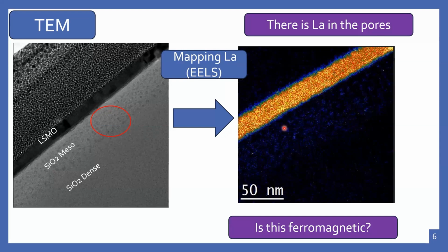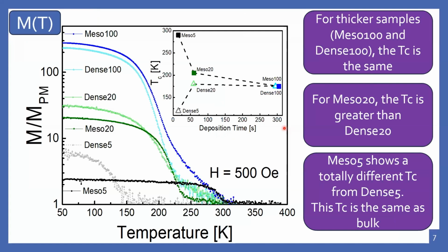So for that, we did a series of magnetic measurements. Here you can see the magnetization against the temperature. We found that all the 6 samples present a paramagnetic to ferromagnetic transition. And the next thing I want to highlight is the Curie temperature.